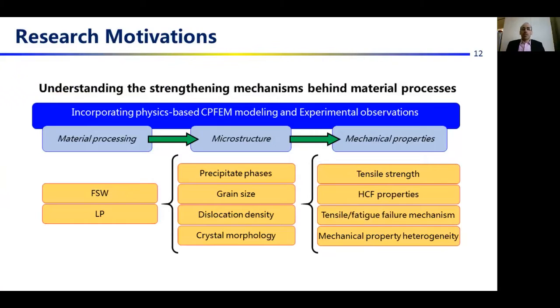In this research, we developed the physics-based CPFEM model to quantify the strengthening contribution of microstructural variations such as precipitate phases, grain size, dislocation density, and crystal morphology during the material processing such as FSW and laser peening to predict the resulting mechanical properties such as tensile strength, fatigue strength, failure mechanisms, and mechanical property heterogeneity.